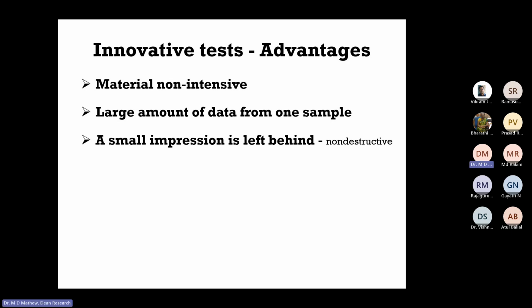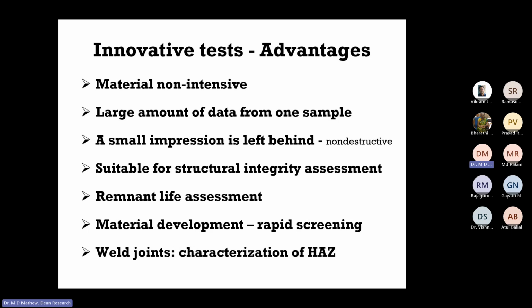So, large amount of data from one sample. And these tests, except in one case, will leave only a small impression in the material. And that is why I call it non-destructive. It will leave only a small impression and maybe some compressive stress. So that qualifies it as a kind of non-destructive test. Therefore, it becomes suitable for structural integrity assessment, assessing the remaining life of materials, and you can use it for materials development. Suppose you are developing a new alloy where you will be making a large number of laboratory heats with minor variations in compositions, and you need to do a rapid screening of this. It comes very handy because these tests are short. You can do this test very quickly, so a large number of these heats can be characterized for screening purposes.